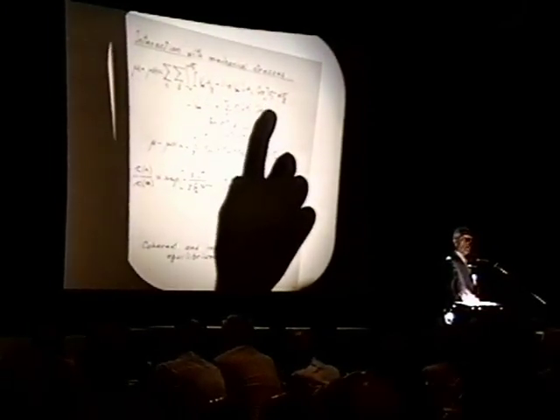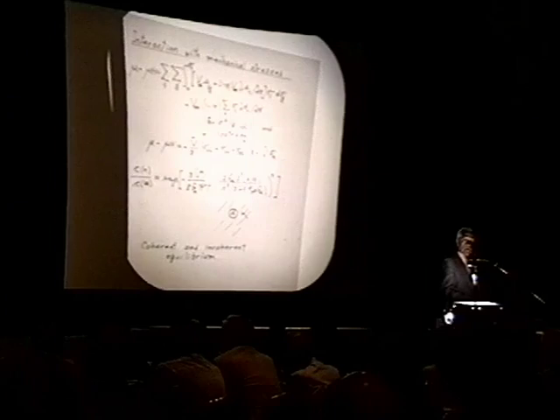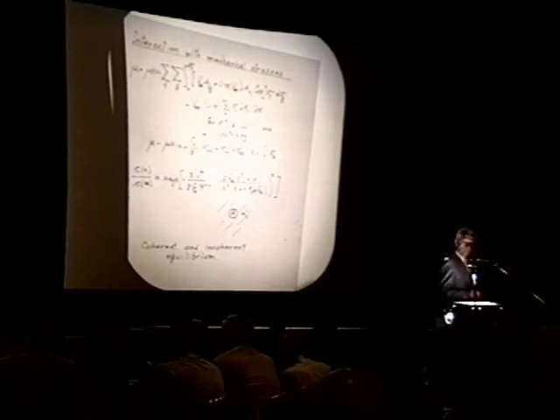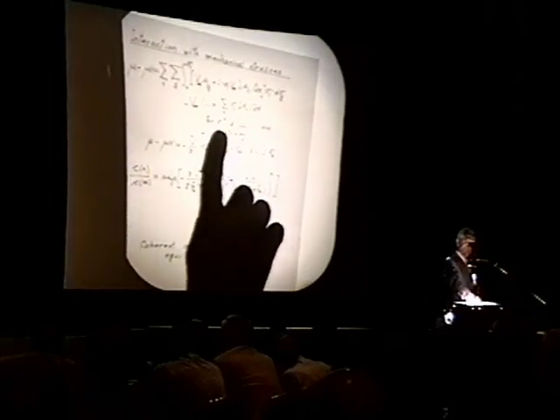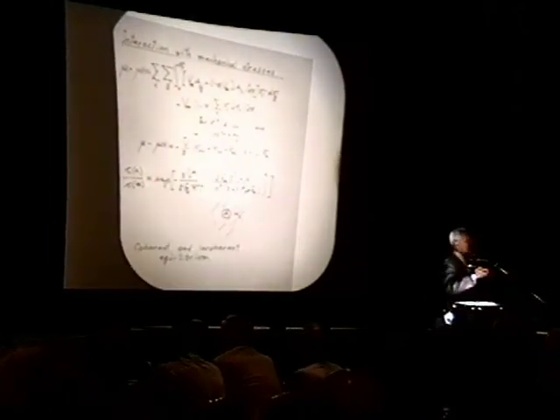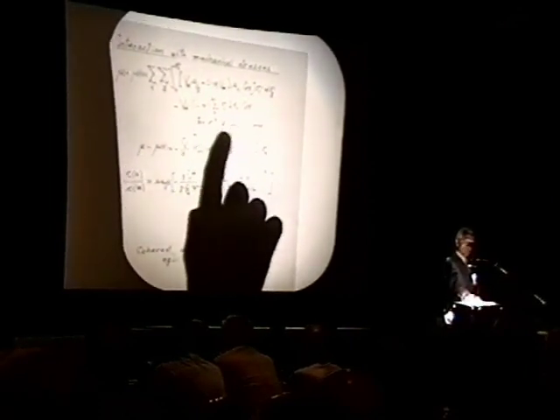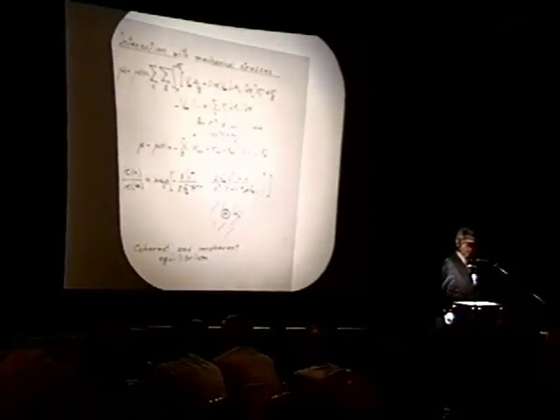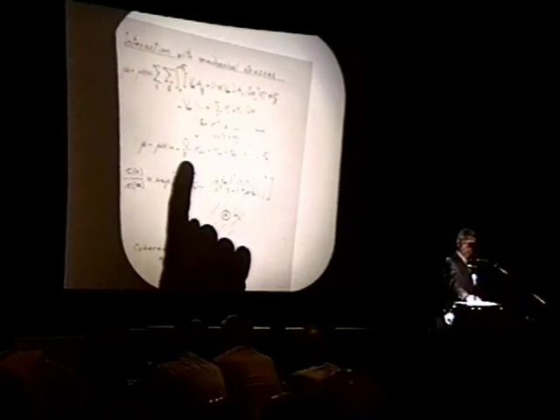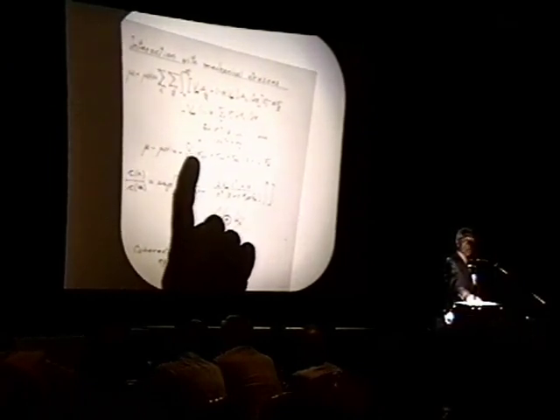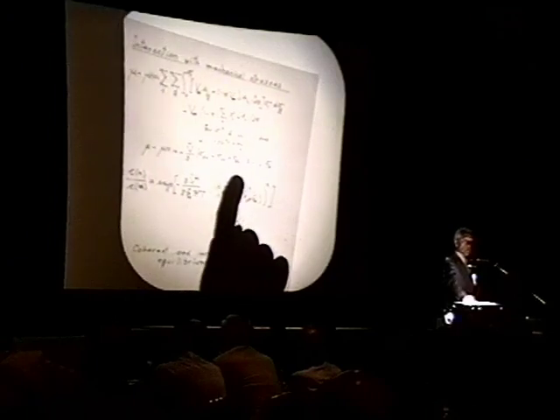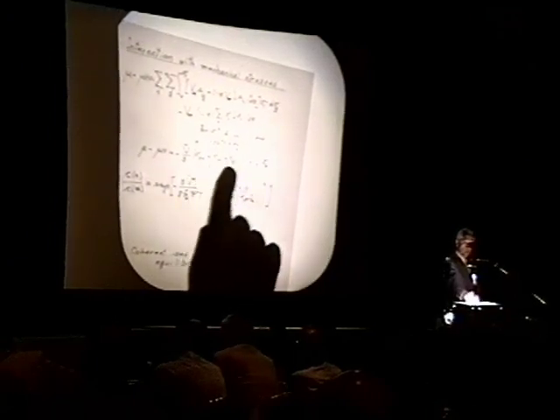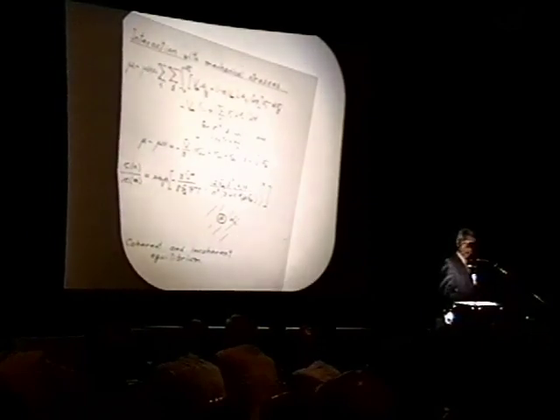Sigma is the stress. Actually, we have to worry about the entire stress tensor here. The convention, by the way, is that sigma, or stress, is a positive quantity when it's tensile. In the case of the square of the stress, whether it's internally generated or externally applied, if that ratio over Young's modulus is a small quantity, and in case of isotropy, this complex equation can be reduced to the simple form where we have the partial molar volume of the interstitial solute times the trace of the stress tensor, one third of which we call the hydrostatic component of stress.